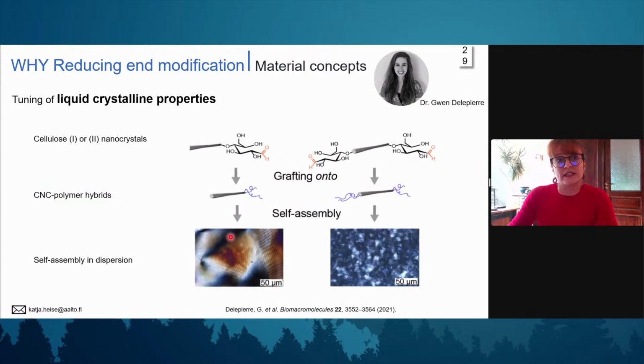And what Gwen was then interested in, and coming back also to the material concepts, is can I actually, by grafting polymer chains from the reducing end groups, tune the liquid crystalline properties of cellulose nanocrystals? And yes, it's something that she can do. So she has grafted polymer chains from cellulose 1 nanocrystals with reducing end groups only on one side, and also cellulose 2 nanocrystals, where you basically have anti-parallel chain alignment and you have reducing end groups on both sides. So after polymer grafting, you get this dumbbell structure, and she has really shown in this work how she can actually tune the liquid crystalline properties. So I really recommend reading this article.